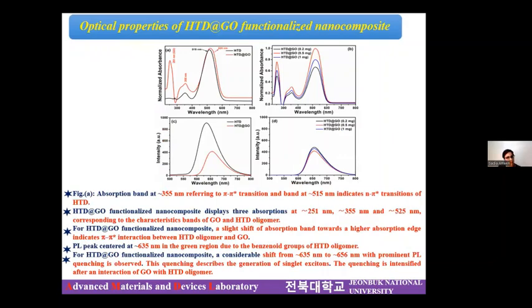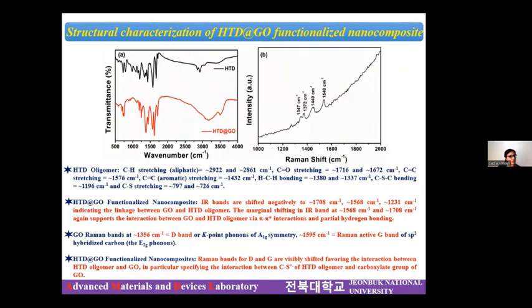And these are some of the optical properties of the synthesized moieties with the graphene oxide, and it exhibits that there are some interactions between the graphene oxide as well as the synthesized moiety, that is HTD, which has been confirmed from the UV spectroscopy as well as from the PL spectroscopy. Then we performed the structural characterization through FTIR and Raman spectroscopy. As we know from the Raman spectroscopy, in case of graphene oxide, the D band generally occurs at the position of 1356, whereas the G band at the position 1595. However, in our case, it has been little shifted, which is due to the incorporation of the HTD material and the interaction of the HTD material with graphene oxide.